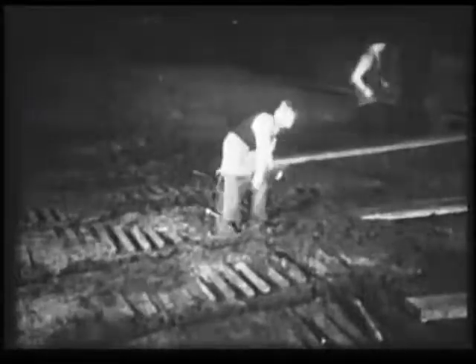Each German steelworker could produce half as much again as his British equivalent. After the Great War, German firms had re-equipped and reorganized into combines and were protected by tariffs. They measured everything. They measured blast furnace gas. They analyzed the blast furnace gas and found out how much carbon was in it. Then they checked that against the amount of carbon put into the blast furnace to make sure that it all added up. It was this scientific approach.